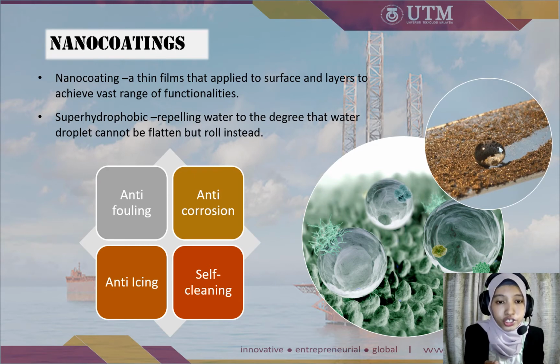Well, the definition of superhydrophobic is repelling water to the degree that a water droplet cannot be flattened but rolls instead. Interestingly, the superhydrophobic coating can effectively prevent corrosion, credited to the presence of air pockets existing between the surface and the corrosion solution, and these pockets act like a barrier and prevent corrosive ions diffusion and protect the substrate.